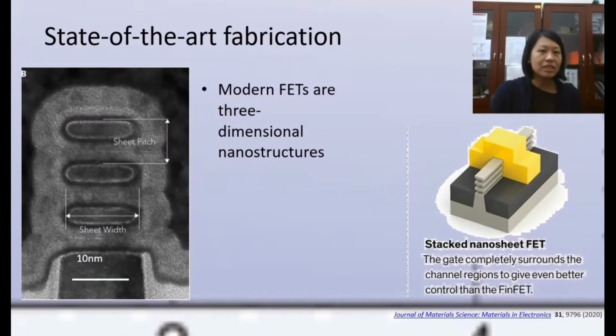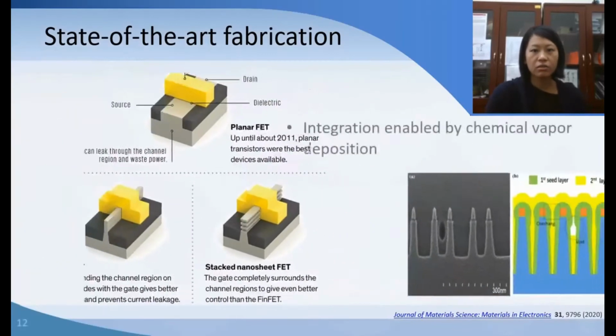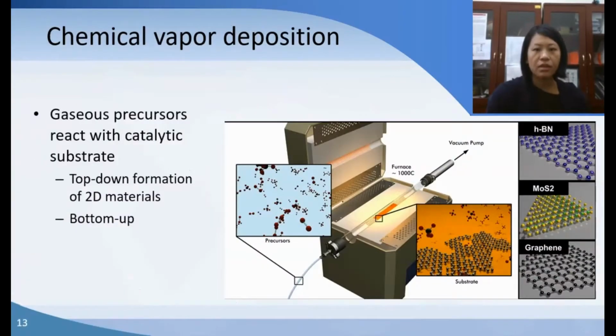And the good thing is that currently silicon is made into already 2D-like. You can see this is how a current transistor works. They made the silicon into like 5 nanometer thick and made it into a multi-layer stack. That is a good thing for 2D material, because we just need to figure out how to grow our 2D material into that confined space. Then we will be able to replace current silicon CMOS. That's why we work on confined CVD growth.